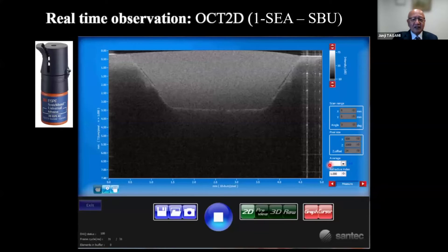This is one of the observations using a universal bond — one of the representative universal bonds, very well accepted in the clinic worldwide, providing very good clinical performance. However, we should recognize that this kind of phenomenon occurs very frequently in the clinic. This is the cavity, this is the composite resin, and this is the cavity wall and cavity floor. When we see the OCT image, a white line indicates the presence of a gap or separation.